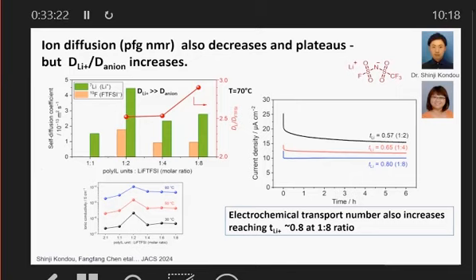And if we then measure electrochemical transport number, as we've done on the right-hand side here, we see that although the overall steady state current goes down because the conductivity has gone down, the actual transport number has gone up to about 0.8. So 1:8, which is still not a single phase, not a homogeneous system, at least not on the macro scale. We see a transport number of 0.8, and at the 1:2, we see the 0.57 that we saw earlier on for the FSI system as well.